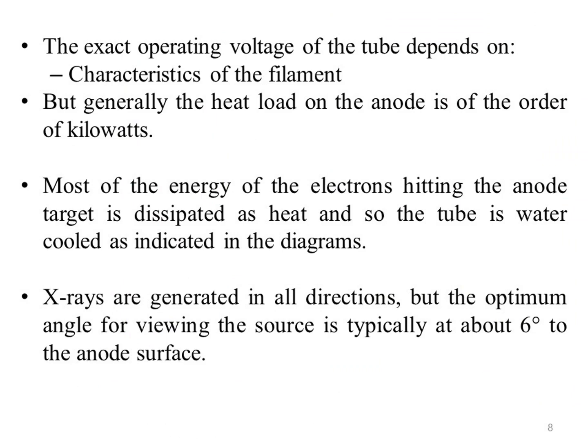The schematic diagram below emphasizes the key aspects behind the operation of the X-ray tube. The exact operating voltage of the tube depends on the characteristic of the filament, but generally the heat load on the anode is of the order of kilowatts. Most of the energy of the electrons hitting the anode target is dissipated as heat, and so the tube is water cooled as indicated in the diagrams. X-rays are generated in all directions, but the optimum angle for viewing the source is typically at about 6 degrees to the anode surface.